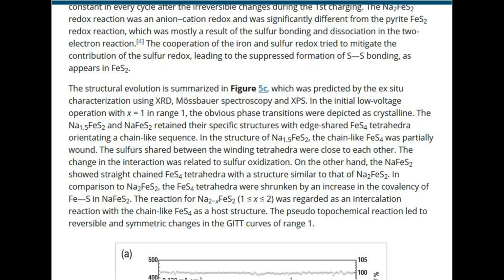The reaction for Na2-xFeS2, 1≤x≤2, was regarded as an intercalation reaction with the chain-like FeS4 as a host structure. The pseudo-topochemical reaction led to reversible and symmetric changes in the GITT curves of range 1.